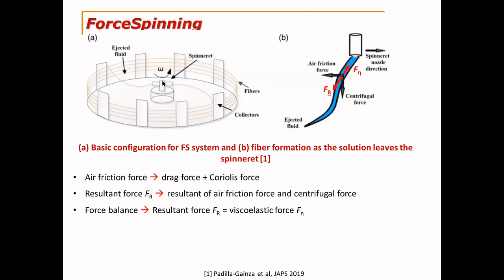So polymer solution is infused in this spinneret, and this spinneret will rotate with a particular angular velocity, which we give. And when this spinneret rotates, centrifugal force shows up, and that results in the ejection of the polymer solution, which travels in a spiral direction, and this polymer jet will get deposited on these collector plates, and finally it will get solidified and the fibrous mats are collected.